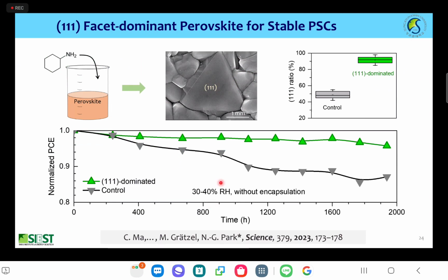Because we know that the 111 crystal facet is quite stable under moisture conditions, we also wanted to make a 111 dominant perovskite film. In that case, we used a different additive, cyclohexyl amine, and we could get over 98% 111 dominant perovskite film. And then we proved the moisture stability of this kind of 111 dominant perovskite film.